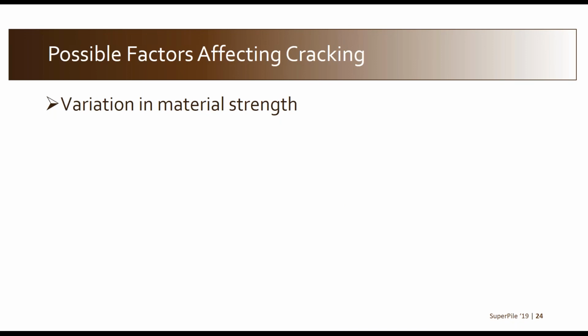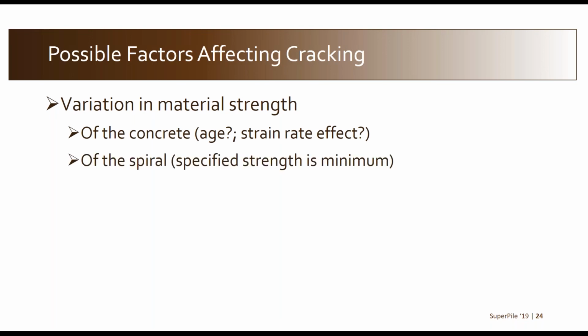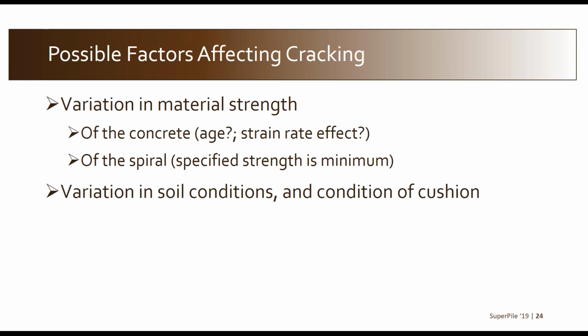So why did some of them crack, but not all of them, was the other aspect we were looking at. And we postulated a number of possible explanations. One, variation in material strength. Even though we know on average the strength of the concrete, for example, was higher than the design specified strength, likely the yield stress and ultimate strength of the steel were as well. There's going to be variability across the site that we don't really have sufficient records to assess, of the concrete and of the reinforcement.